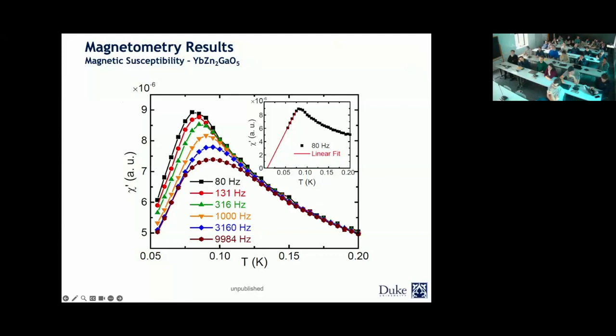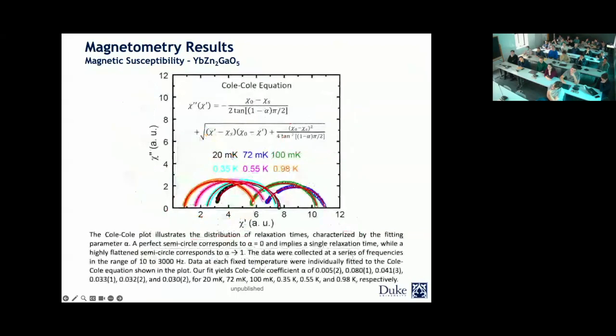However, the good news is that when you look at the lowest frequency and you try to do a linear extrapolation of that, you can see that it crosses very close to zero. So that's a good indication that at least it doesn't get to a finite value that would be a glassy nature or something that makes things complicated. Okay, but we didn't stop there.